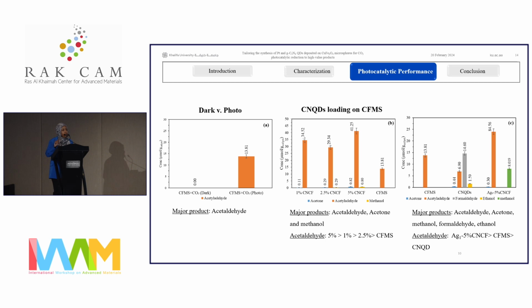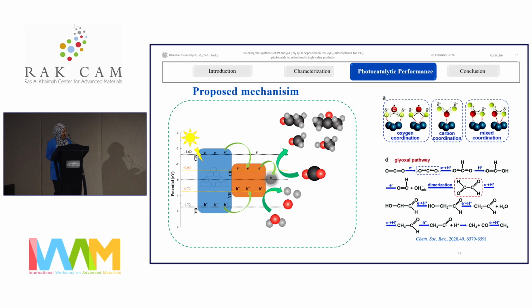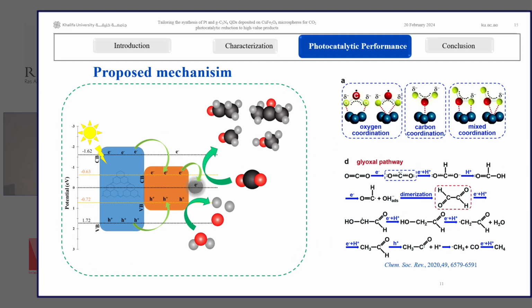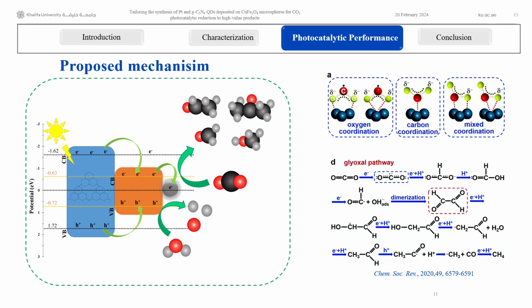The final stage was using the nanocomposite that gave us the best performance, and we deposited silver nanoparticles on the nanocomposite, which doubled the yield, and we ended up forming 84 micromole per gram of acetaldehyde, in addition to methanol, acetone, and formaldehyde. So, based on the obtained products, we deduced that the most probable mechanism would be the glyoxal mechanism, which yields C2 products.